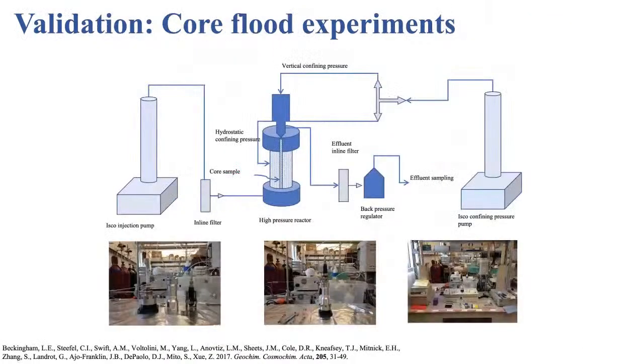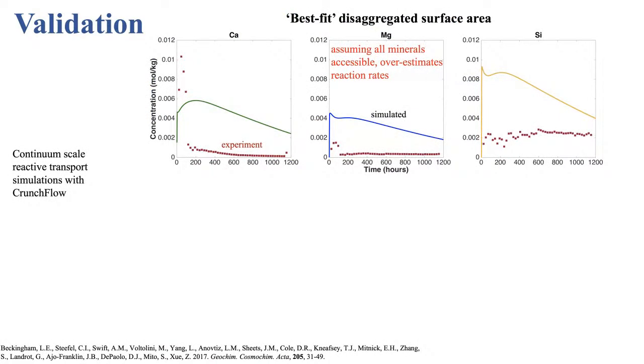We validated this with core flood experiments and then carried out continuum scale reactive transport simulations of the experiments with CrunchFlow. When our simulations used or assumed that all mineral surfaces were accessible, we really overestimated the extent of reaction happening in experiments.